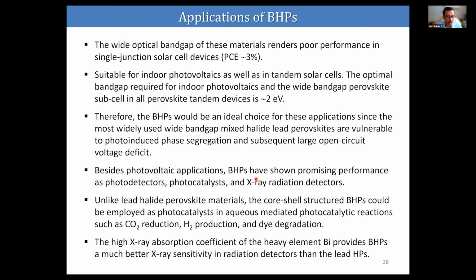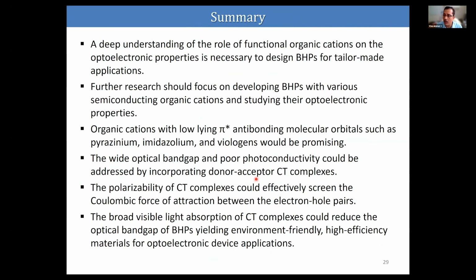And unlike the lead halide perovskite, these core-shell structured bismuth halide perovskite could be employed as photocatalyst in aqueous mediated photocatalytic reactions for carbon dioxide reduction, hydrogen production, and dye degradation. And they can also be used as X-ray sensors, because they show a very good X-ray absorption coefficient because it belongs to the heavy element category. So in summary, a deep understanding is required of the role of functional organic cation on the optoelectronic properties of bismuth halide perovskite for tailor-made applications.